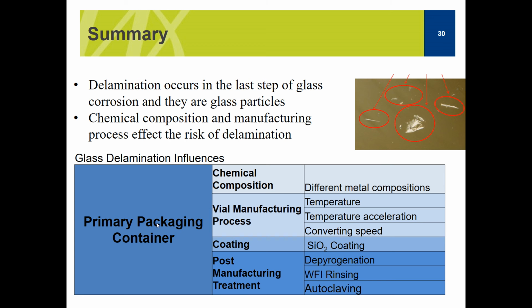Okay, so in summary, delamination, or lamellae formation, occurs as the last step of glass corrosion. So glass corrosion and glass attacks happen early on, and at the end, after everything's said and done, then you'll see this glass delamination. Changing the chemical composition and changing the manufacturing processes can affect the risk and the probability of lamellae formation. And again, I'm 95% certain that the DC delamination control vials by Schott and the Vial-X by Nipro are either changing the glass composition or changing the manufacturing processes, and most likely they are changing manufacturing processes because it's extremely difficult to change the chemical composition. So they're basically changing the speed and the temperature at which the vials are being manufactured and formed.